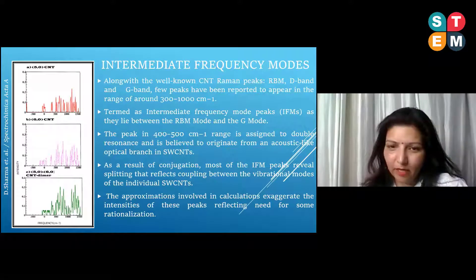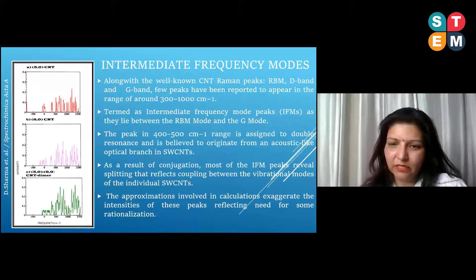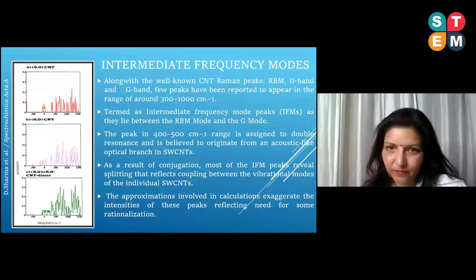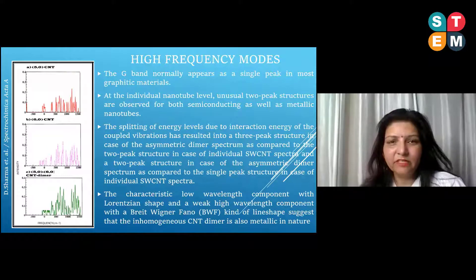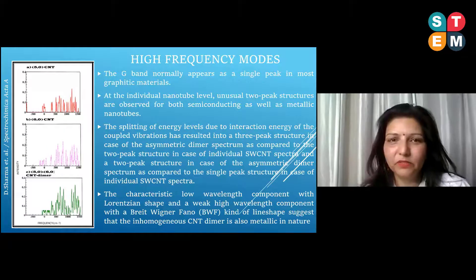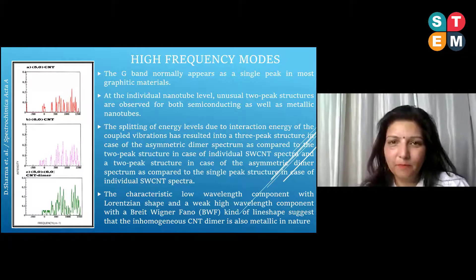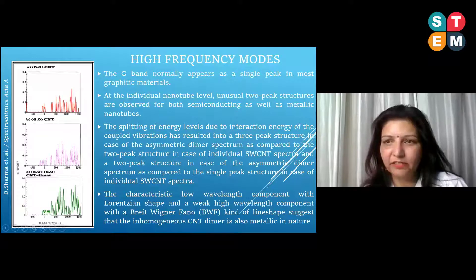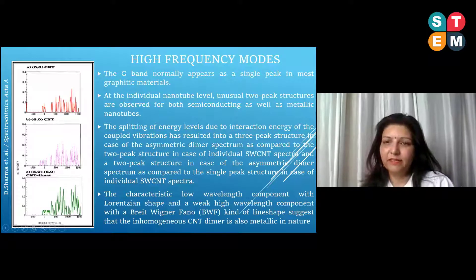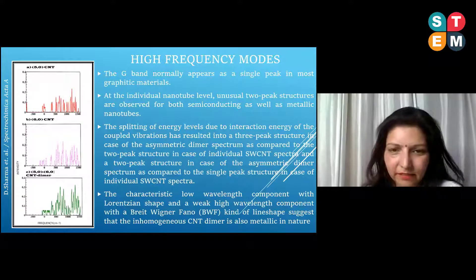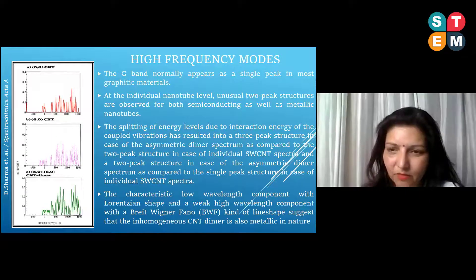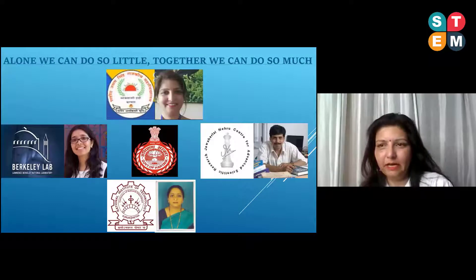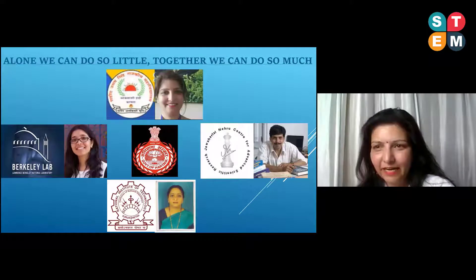Though we used certain approximations because of which intensities are slightly exaggerated, in the high-frequency modes the G-band normally appears as a single mode, but splitting of energy levels due to the interaction energy of coupled vibrations has resulted in a three-peak structure in the case of this asymmetric dimer. These are some of the studies I have shared with you.